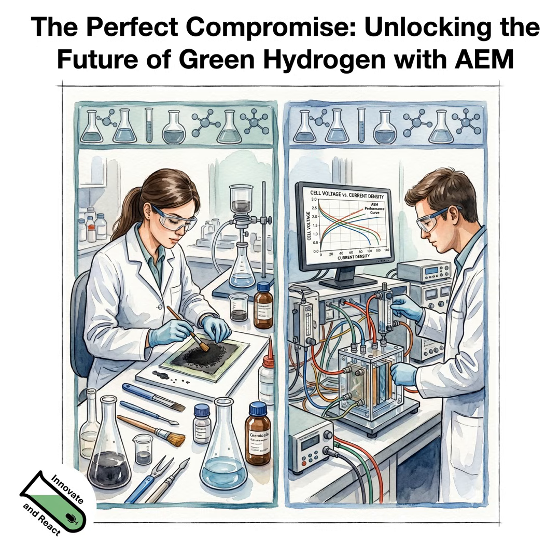So for the anode side, we have a higher hydroxide layer on the surface, which improves the oxygen evolution reaction and creates stable hydroxides on the surface. And for the cathode, it also improves the hydrogen evolution reaction compared to when we only have a nickel hydroxide without the sulfur. And this is because during our electrochemical characterization, using impedance spectra for example, we observed that the electronic conductivity with sulfur is better than having only nickel on the cathode side.